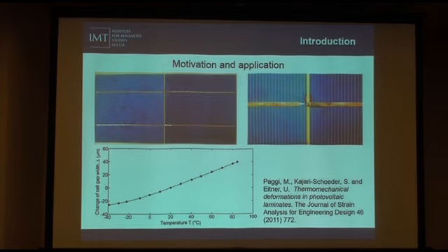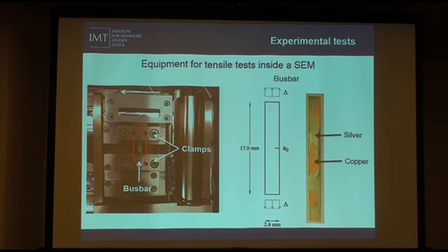We apply the theory to a material that is used in busbars. Busbars are the metallic strips that electrically connect photovoltaic cells. This strip can suffer tensile stress and fatigue due to thermal excursion. In fact, it has been studied that the gap can increase by about 60 micrometers, that is a 3% strain.